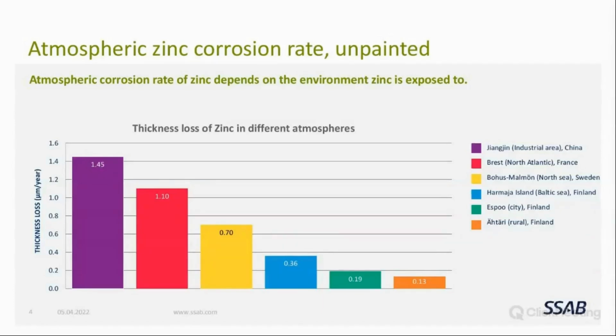The most demanding area is Jiangjin, which is heavy pollute industrial area, and there the thickness loss is around 1.45 micrometers per year. And the lowest end is Ähtäri, which is a rural area, and there the loss is around 0.13 micrometers per year. So it means that climate itself means a lot.